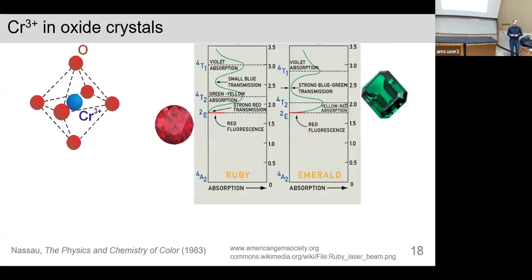And then a really common impurity in all kinds of oxides is chromium, and specifically the 3+ oxidation of chromium. And here's an example of chromium in some crystal, and it's in an octahedral environment. So it's surrounded by 6 oxygen atoms, and the dashed lines show this 8-sided shape. It's called an octahedron. And chromium can be in various crystals. If it's in aluminum oxide, we call it ruby.